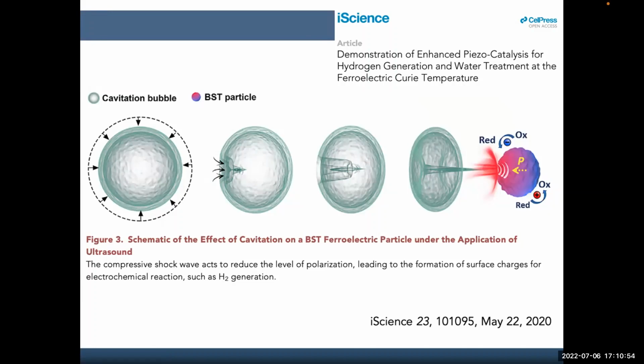I guess the challenge in a lot of the ultrasound experiments is it adds a lot more complexity to the experiments because you have sonochemical effects. So I think when people are doing this work, it's important to do control experiments, add non-ferroelectric particles, or add just the solution without the particles as well. And that's where we work with Professor Phuong in Vietnam Academy of Science, because there's very nice, careful control experiments to try and understand these more complex systems.